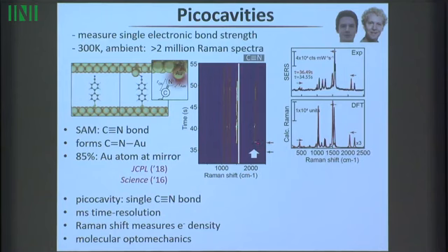And we can make some sort of DFT calculation which looks nicely in comparison to the data, but then again we're still making this incredible assumption that we can treat our gold atom as a classical object, and that the DFT is not done with all the gold atoms around and all the electrons, so there's a lot going on here. So this is now a new field that's called molecular optomechanics. It's essentially something vibrating coupled very strongly to molecules and also to this optical cavity. And trying to do all the quantum of this together is just beyond what people are able to do. So again, I hope I'm trying to convince you about this classical quantum boundary.